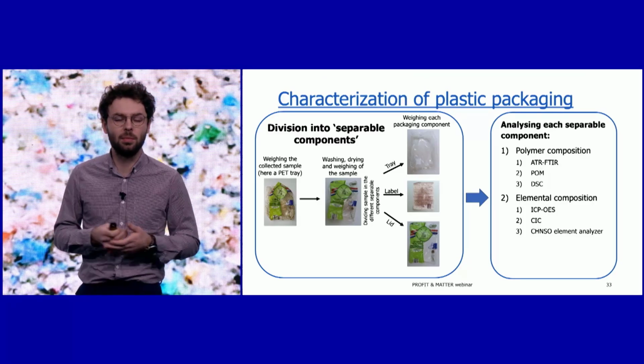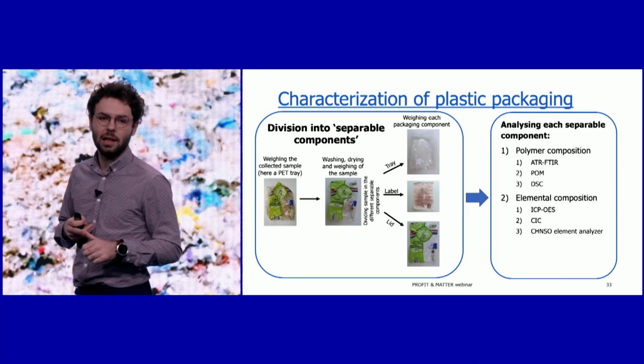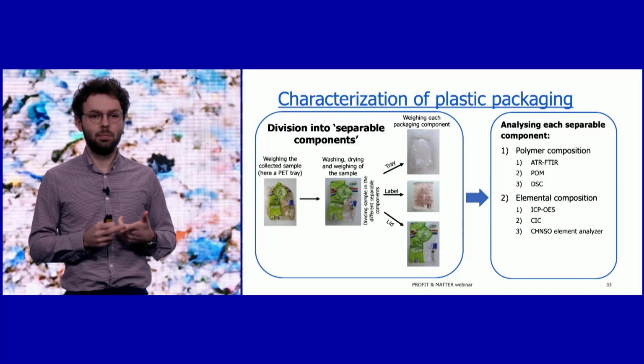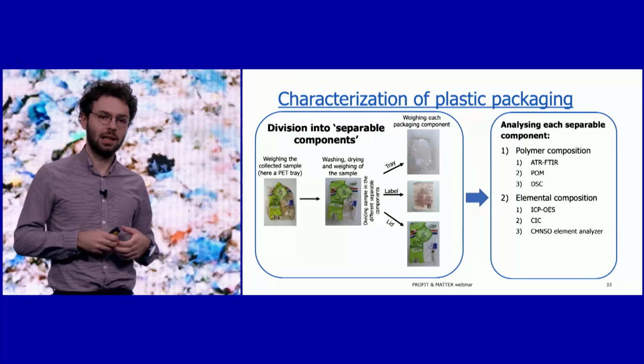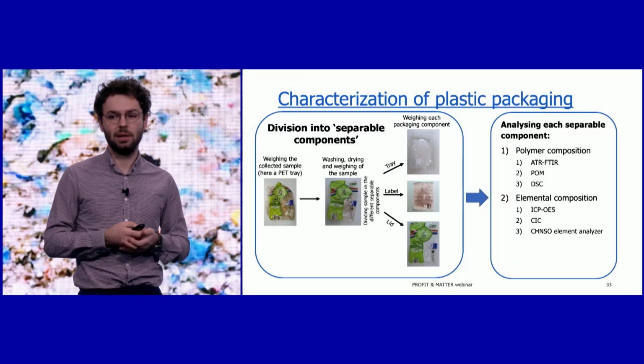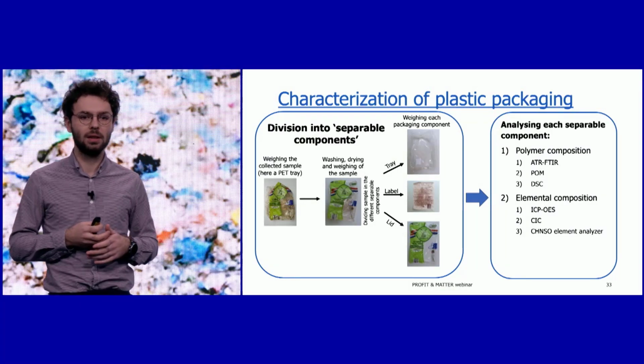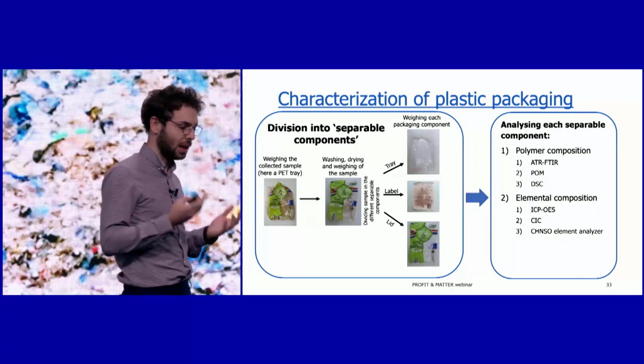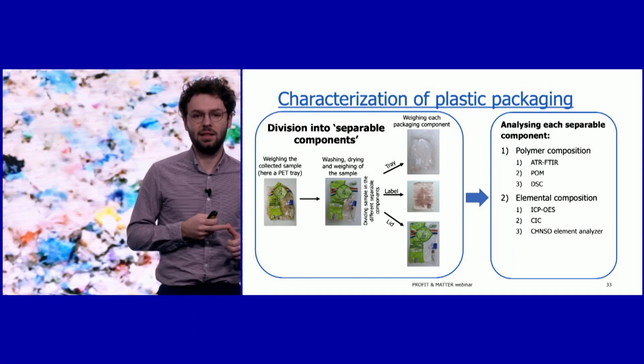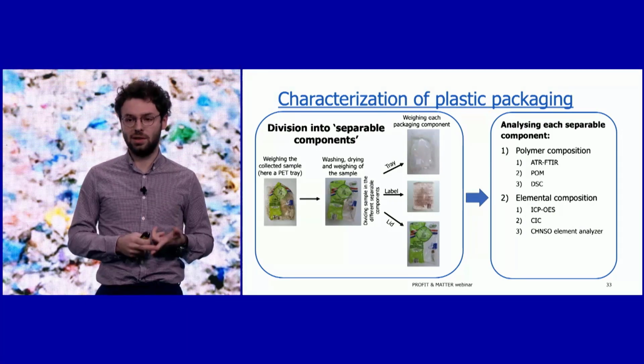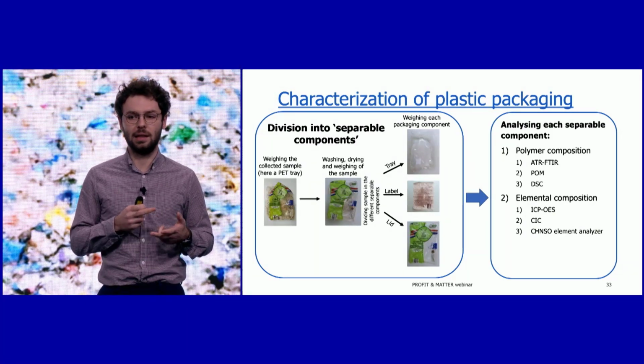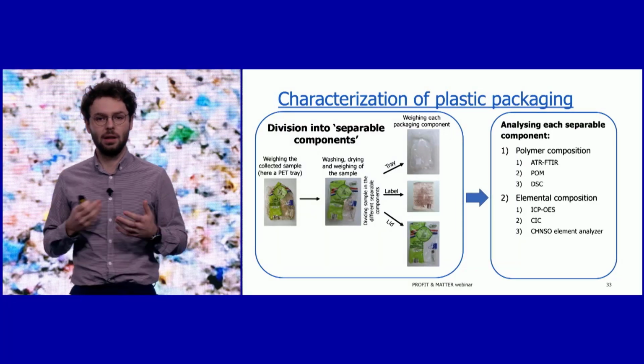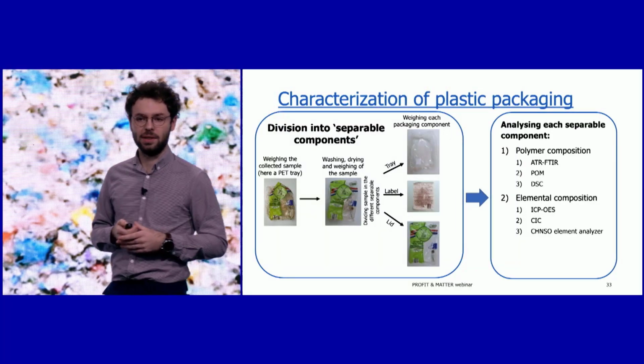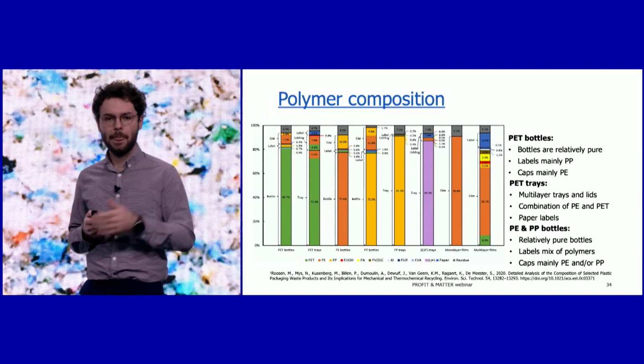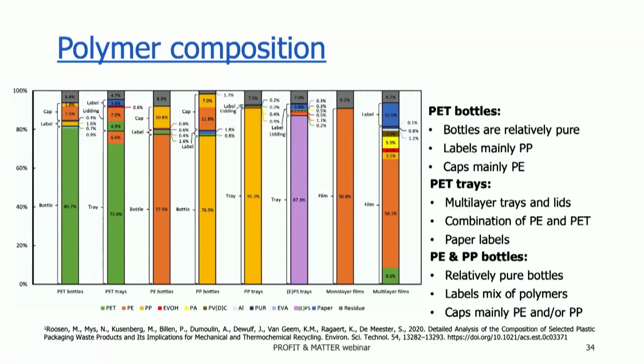On each component we applied ATR, FTIR analysis, POM analysis, and DSC analysis to characterize them in terms of polymer composition. We also applied ICP-OES analysis, combustion ion chromatography analysis, and CHNSO analysis to get to know the elemental composition. And here on this slide you can see the polymer composition.